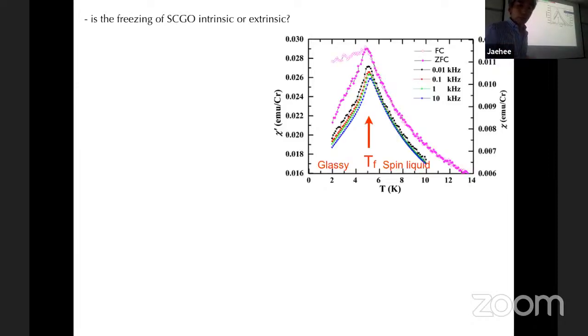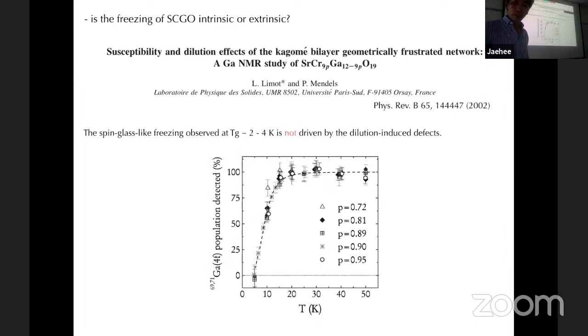Okay, the question some may ask is whether this transition is intrinsic or extrinsic, because we have this non-magnetic mixing problem, and there were two camps back in the 1990s. But Philippe Mendels, the NMR guy, did very careful measurements, and the conclusion was that this spin glass-like freezing is intrinsic, not extrinsic. But that, I think, is consistent with Arthur Ramirez's data also.